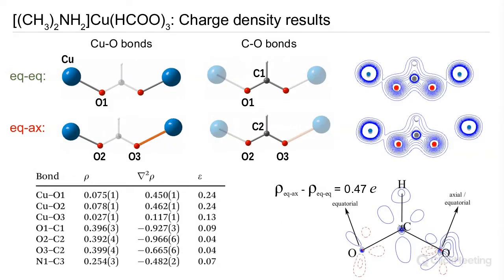We can quantify these differences by looking at the bond critical point, plotting the charge at that critical point and calculating the Laplacian. If we look at the oxygen-carbon bonds, the first thing we see is that the quantities are very similar for the two formates. These numbers are characteristic of a covalent type bond, where there is appreciable electron density localized on the bond. We also see similar parameters for the copper-oxygen bonds, which are more coordinative in character, with the copper-oxygen 3 bond being the most ionic, let's say.